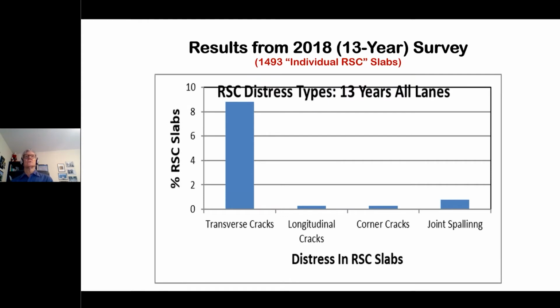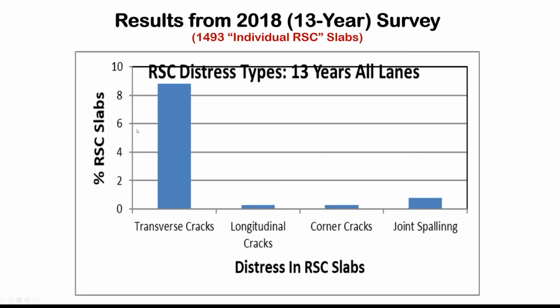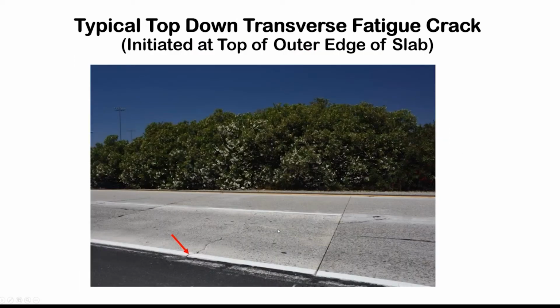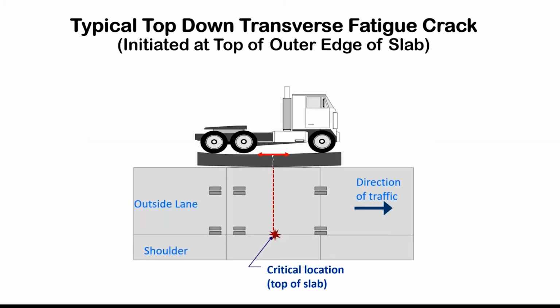Okay, let's look at the results here. Here's the 13-year study from 1,493 slabs. Percent slabs on the vertical axis there, and you can see out of all those distresses, the only one that matters, that showed anything, is about 9% of the slabs showed some transverse cracking. But as far as the other kinds of cracking, virtually nothing. So what is this transverse cracking? Well, this is just the well-known fatigue cracking that we try to prevent in pavement design. We design for this with an adequate thickness and joint spacing and support to prevent it from happening.